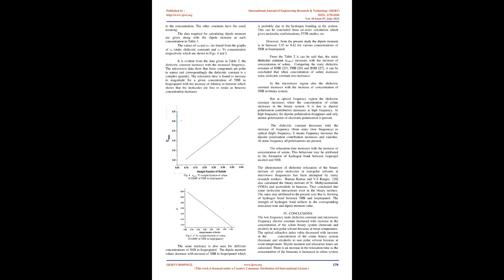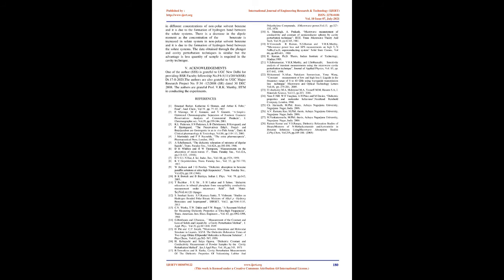But in the optical frequency region the dielectric constant decreases when the concentration of solute increases in the binary system. It is due to the dipolar polarization contribution decreasing at high frequency. At high frequency the dipolar polarization disappears and only atomic or electronic polarization is present. The dielectric constant decreases with the increase of frequency, from static, low frequency, to optical, high frequency. It means as frequency increases, the dipolar polarization contribution decreases and vanishes. At static frequency all polarizations are present.